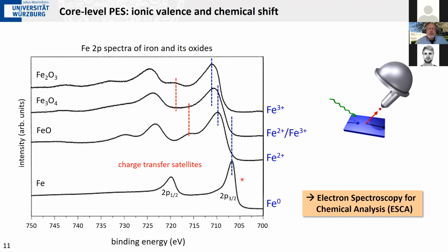And this is related to two things. First of all, the increase in binding energy is due to the fact that as the valency increases, we have fewer 3d electrons in the valence shell. And because the 3d electrons are not only sitting a certain distance away from the nucleus, but also have a finite probability to stay around the nucleus of the atom, this charge is lost and can no longer screen the nucleus. So for a 2p electron that is measured here, the nucleus seems to become more and more positively charged because we lack more and more 3d screening charge, and that's why the binding energy appears to be higher.